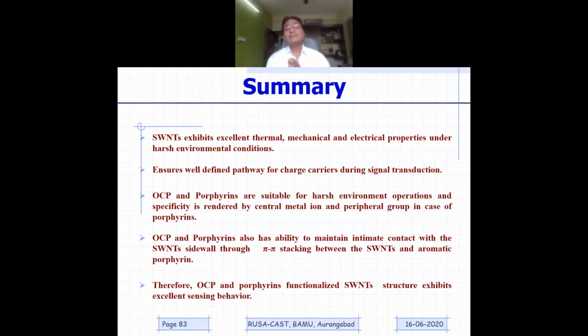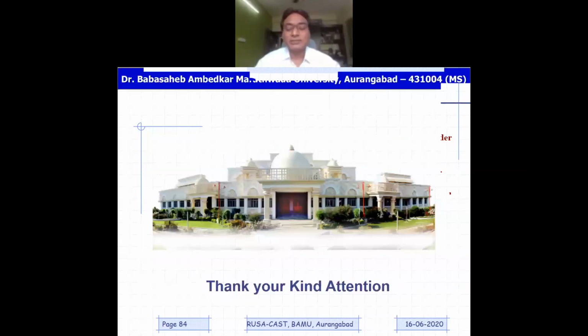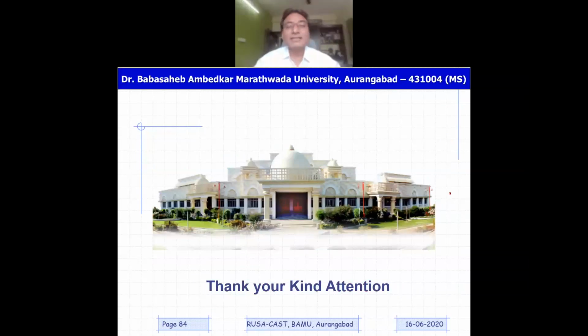As far as the modification with porphyrin, you don't need to do anything special. This is just drop casting. You prepare a porphyrin solution, drop cast it, and incubate it for a specified time. Of course, the incubation time needs to be optimized, from several seconds to a few minutes, so that you don't get complete coverage. You want specific coating of porphyrin on the CNTs.